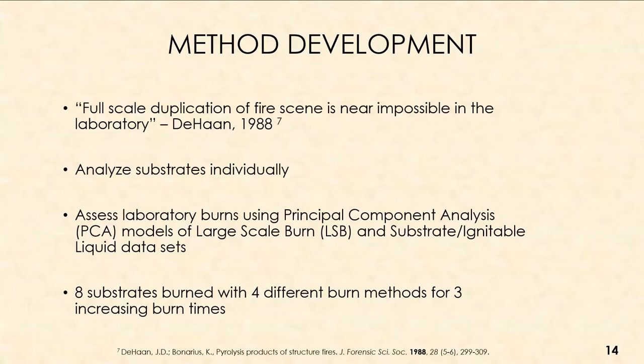For method development, I drew on DeHaan's statement that full-scale duplication of a fire scene is near impossible in the laboratory. I wanted to analyze substrates individually within the laboratory and piece everything together. To do that, I assessed my laboratory burns using principal component analysis (PCA) models on two different data sets — large-scale burns and substrate/ignitable liquid data sets. I burned eight different substrates with four different burning methods at three increasing burn times.